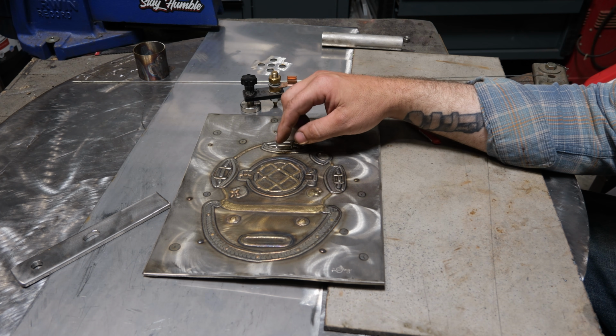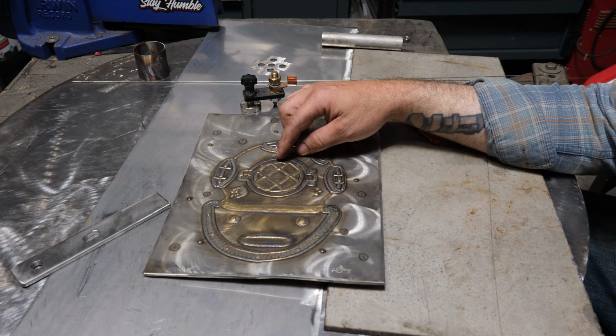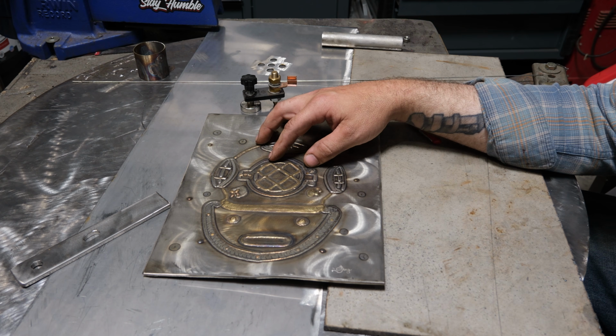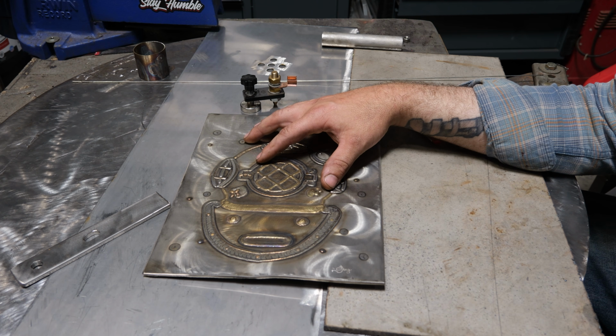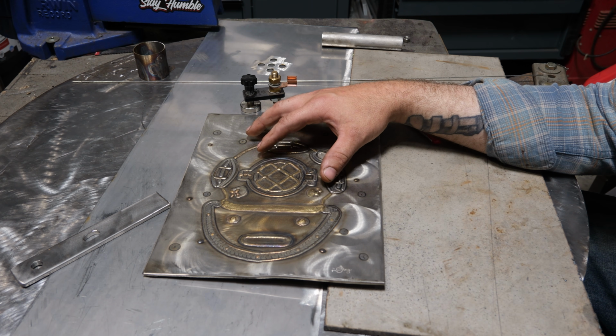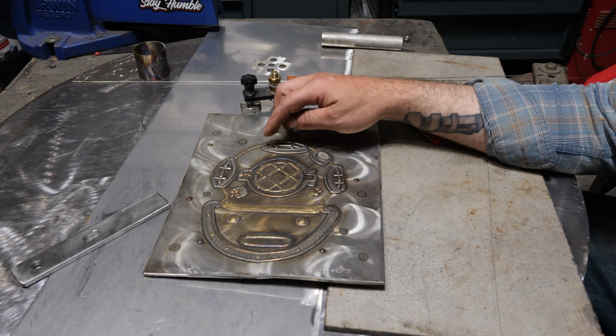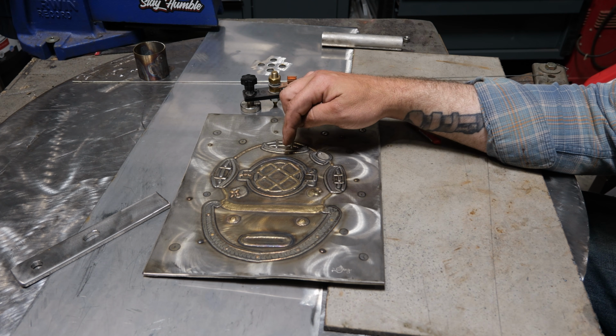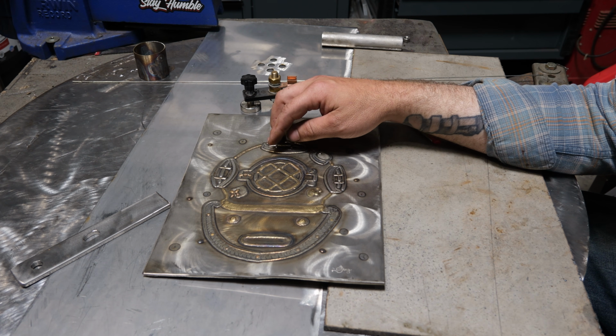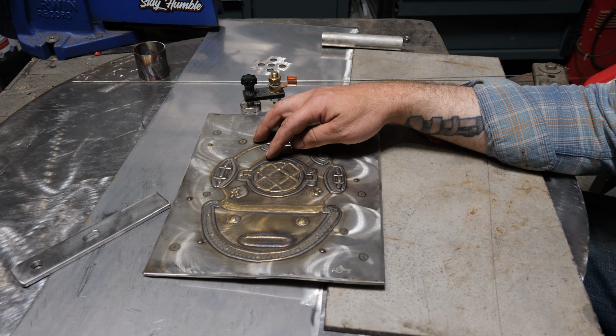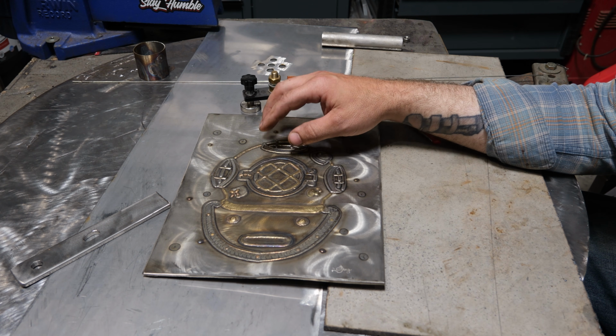Where the problem comes in with stainless is when you weld it and it turns cooked gray, and I'll show you some of that in this video later. That becomes a problem because that level of oxidization is going to be far beyond the surface. It's going to be into the base material. It's not going to be easily removed. You're going to have to grind it all out, and it will rust.